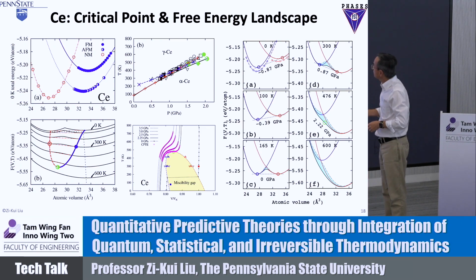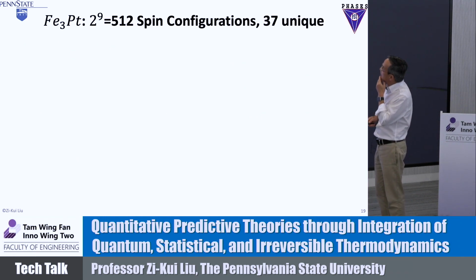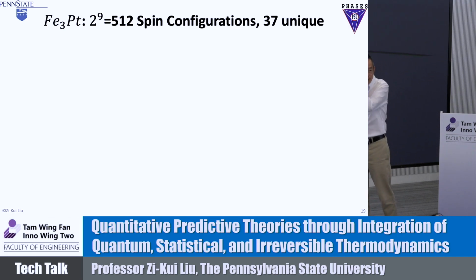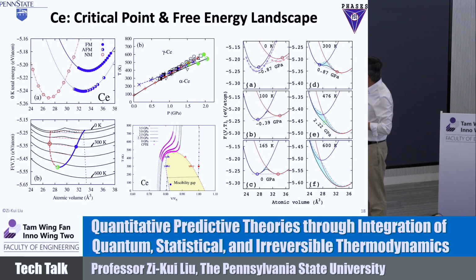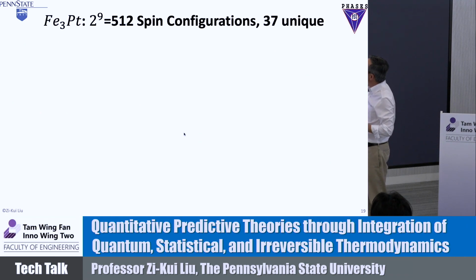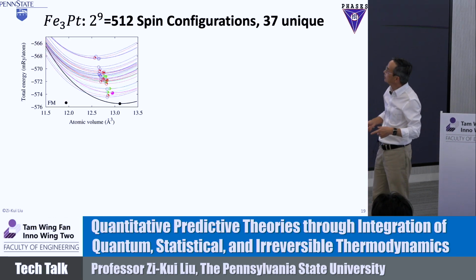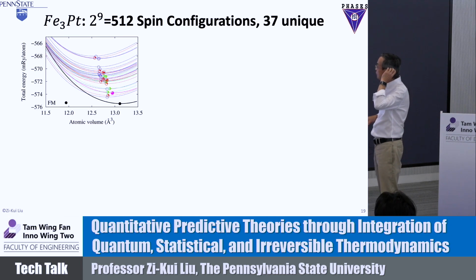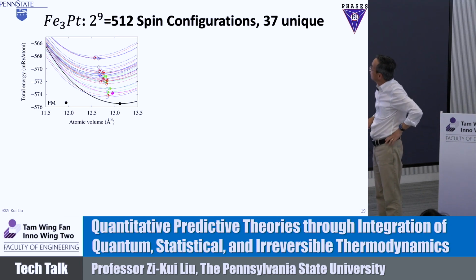All right, so we did another example, iron 3 platinum, that's Invar. Remember, in the previous slide I showed the volume, the thermal expansion is positive, right? The slope is positive here, always goes up. But the Invar alloy is different. In Invar alloy the volume is going to decrease. Again, we take the 512 spin configurations, but 37 are unique.